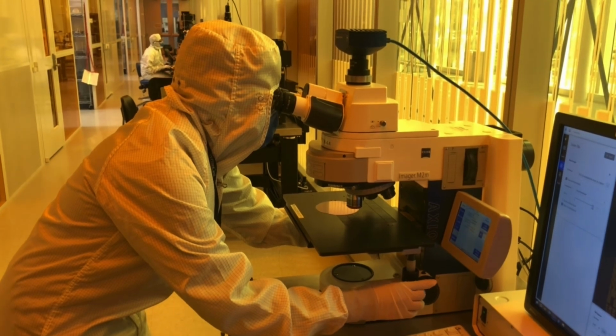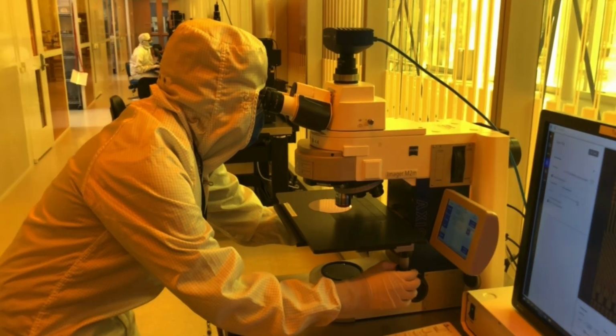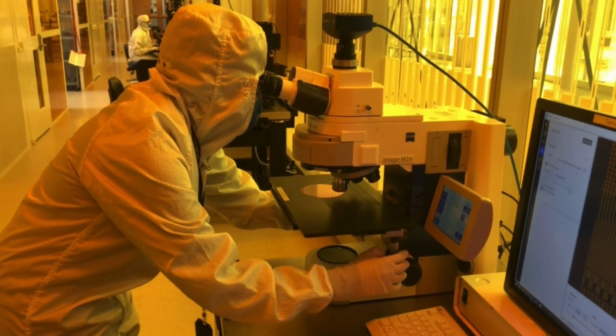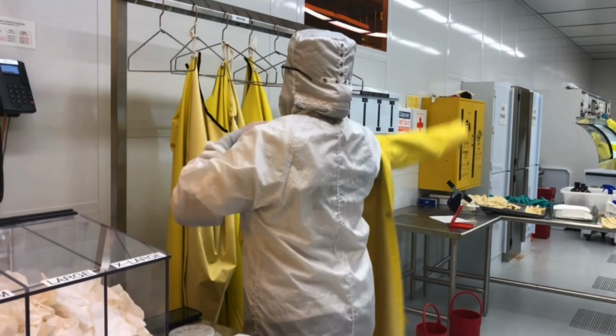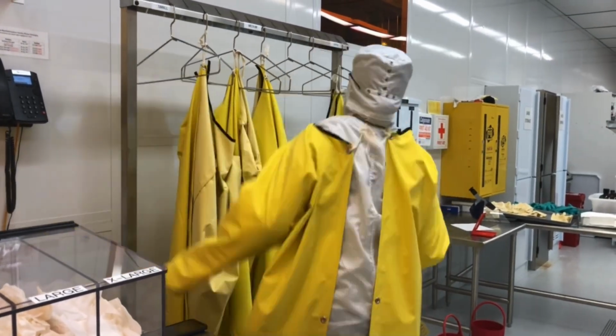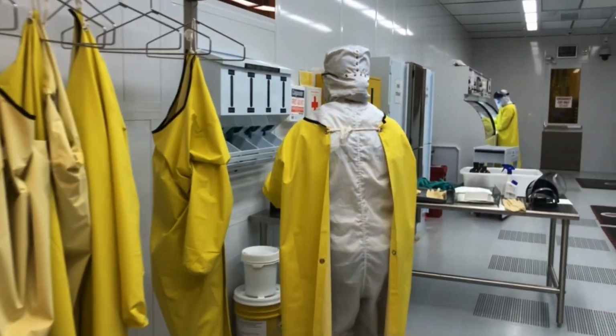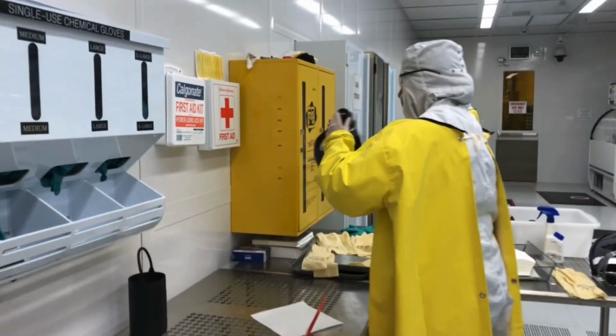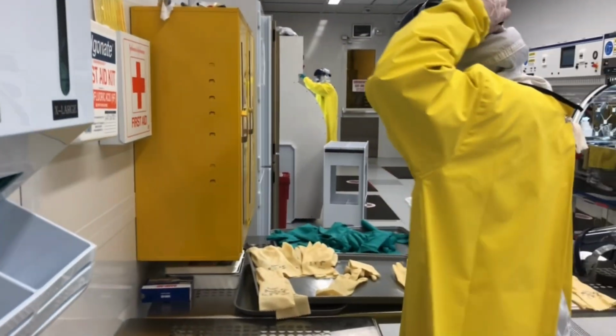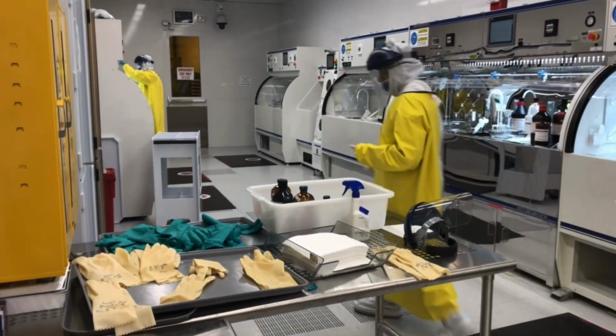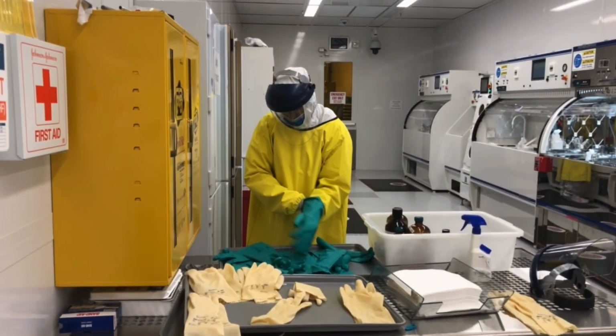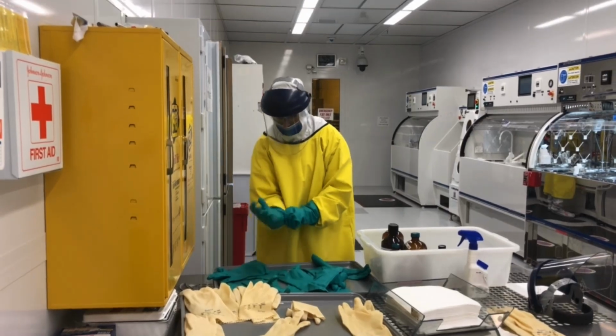The potassium hydroxide etches the 100 crystal plane at an angle of 54.7 degrees relative to the 111 crystal plane. If done correctly, this makes an empty upside-down square-based pyramid in the silicon layer. Lastly, my lab mentor Pia Bhatia carries out an isotropic buffered oxide etch back in the Quattrone Nanofabrication Facility, which removes the remaining silicon oxide.